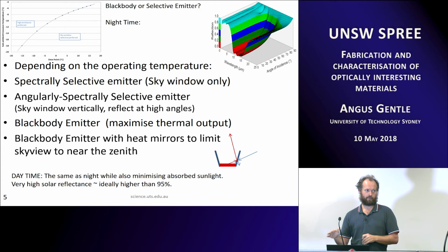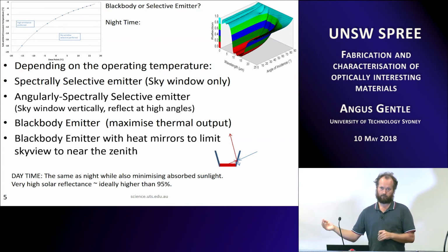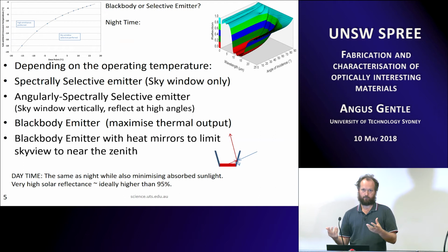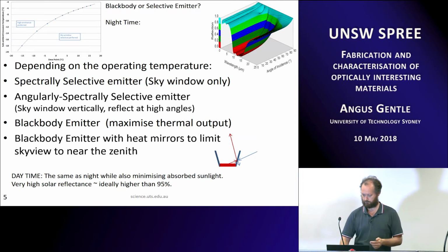If you're above 90% reflecting, you can be below ambient almost the whole year. If you're above 95%, you can be below ambient all the time. So basically, if you've got 5%, you're getting about 50 watts per square metre of sunlight being absorbed, and that's about how much you can radiate out and stay at or below ambient easily.